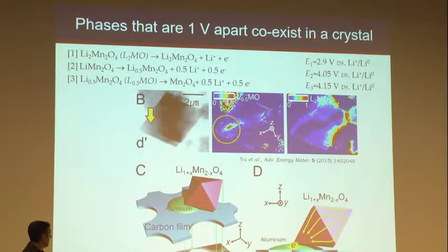And so what we concluded was going on in here is that we have this particle that is quite high. It's an octahedron, and it's about 4 microns in the longest dimension. So gravity dictates that it's going to most likely fall on one of the faces on the grid. And so it's not completely in contact with the grid, and the grid is the only place where the electrons can conduct. There's nothing else. There's no carbon in this. And so what we think is going on in this particle is that this end is touching the TEM grid.